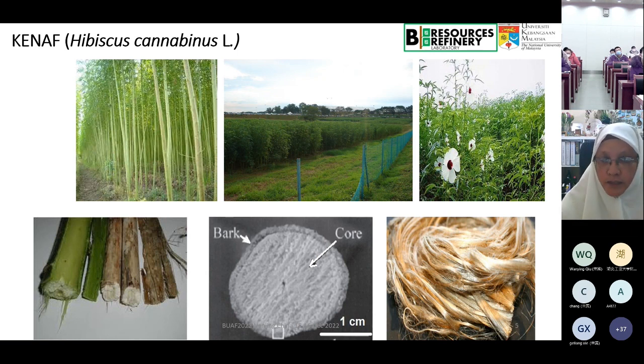which can give you a good proportion of fibrous materials. The core, which absorbs so much moisture, is very hydrophilic and has a very high pore structure, and has been utilized a lot for low-end use. For example, for oil spillage, animal beddings, and so on and so forth. For those who are working in composite materials, the bast fiber has been used a lot. As for textile materials, weaving it together with the polymer, and then pressing it to make a very good composite for automotive and other applications.